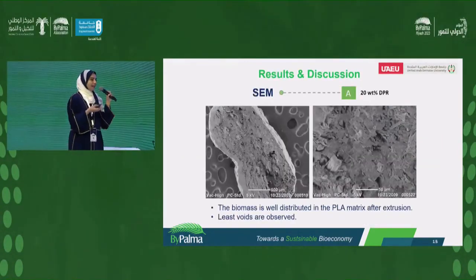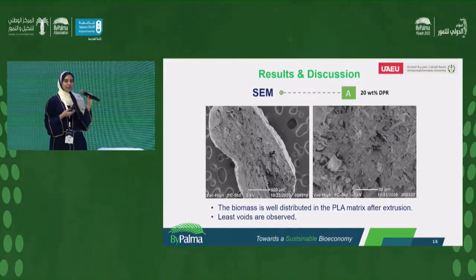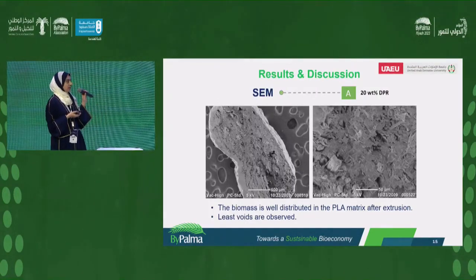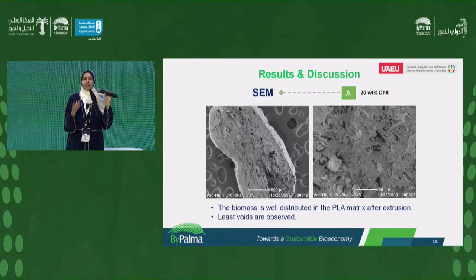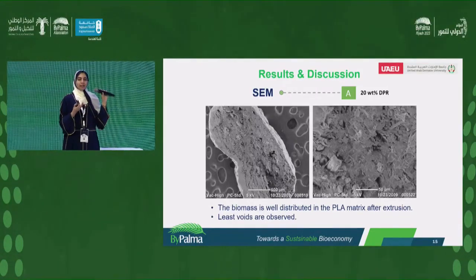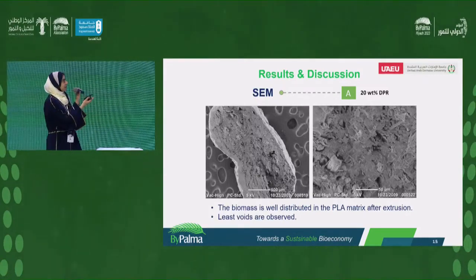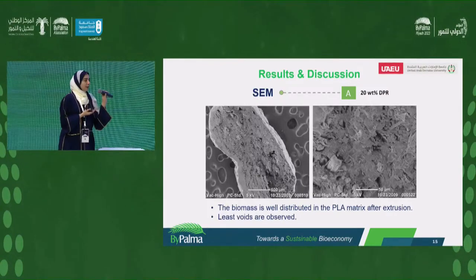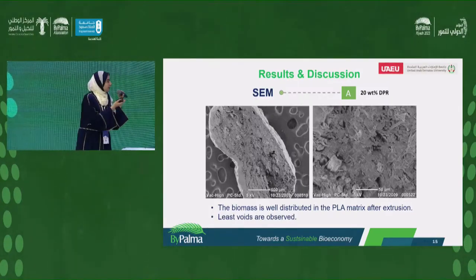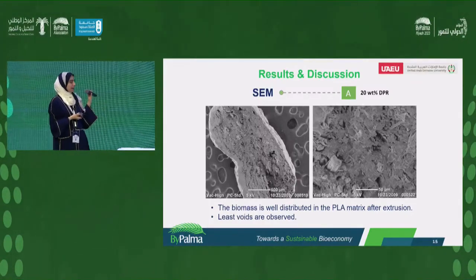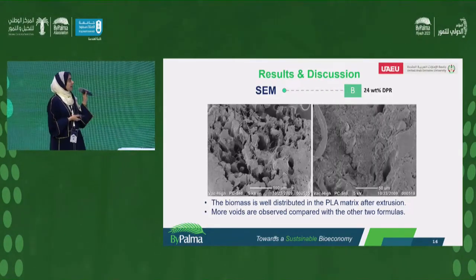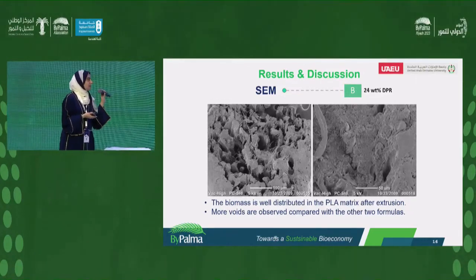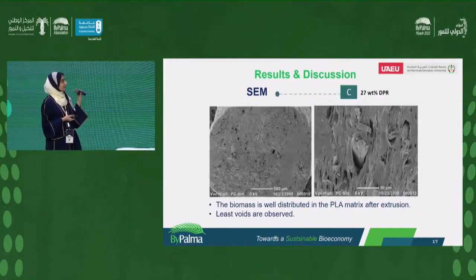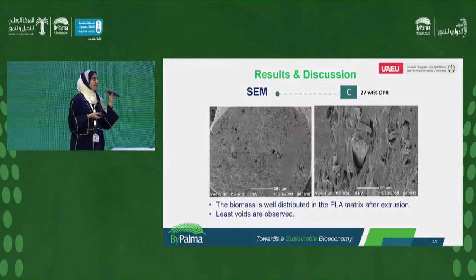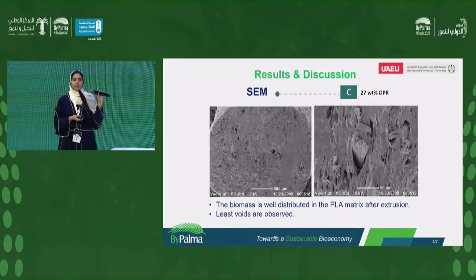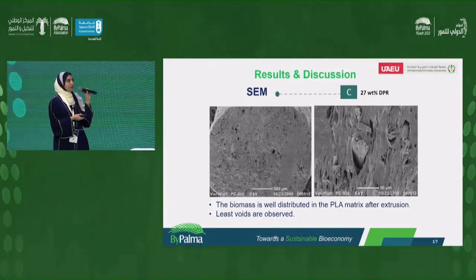Moving to the SEM, let us dig deeply and see the composite using scanning electron microscope. As we know, the PLA, the polylactic acid, is a continuous phase, and the fibers, date palm waste, are like aggregates of entities that have nanofibers on the surface. The first composite with 20% date palm rachis waste, and optimized, of course, we can see the biomass is well distributed in the PLA matrix, and least voids are observed. For the second composite, actually the biomass is well distributed, but we notice that more voids are there. For the third composite, the biomass is well distributed and least voids are observed. So we can go up to 27% biomass in the optimized formulas.